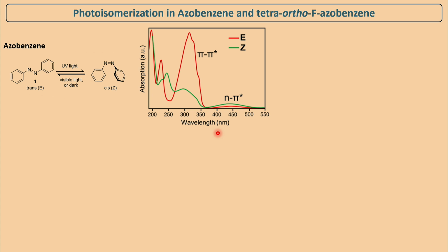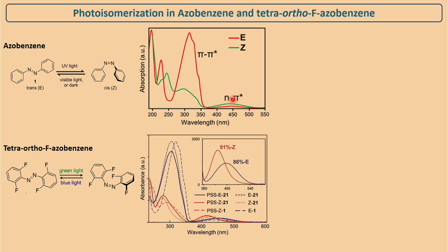And you can see typical azobenzene, if you look at, this is typical azobenzene. I was saying that from trans to cis, if you want to go, you have to use UV light, and you can reverse it using visible light, or you heat it up, then it comes back, right? And typically you see the UV-visible spectra, it is like that. On the E azobenzene, you have this pi star transition. For that you get this particular band around 300 or so, and you get the n pi star band, which is something like this, 450 is a peak. But what happens if you convert into Z, you see that the pi star band goes down and your n pi star band comes up in this particular photoswitch conversion.